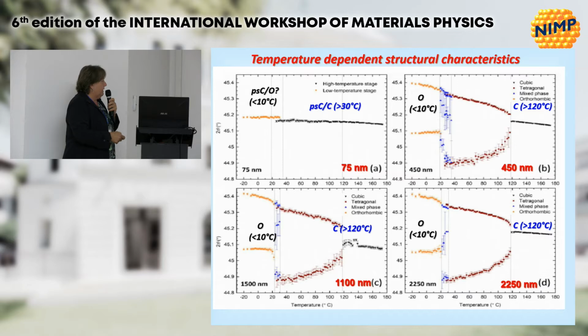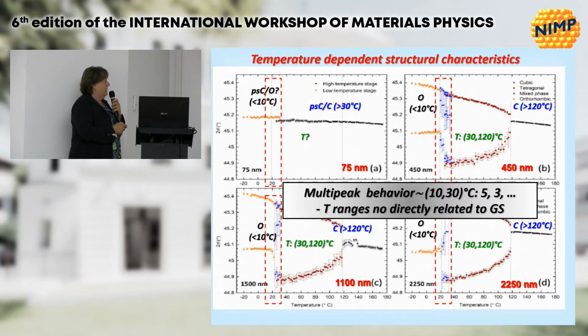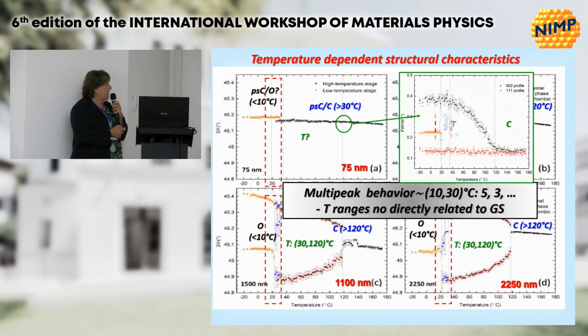We found cubic states above 120. Here again, we couldn't see any phase transition, but nevertheless, we detected it. Tetragonal in the middle, with a large range of phase superposition around the temperature, which, if you look better, tends to become larger. Here is large, but here is a big mess. And this temperature range becomes thinner when you increase the grain size. So we have a multi-peak behavior for all the samples. It is not only specific to small grain size, like it was reported and like it was calculated by Landau models, but it is present for everything.